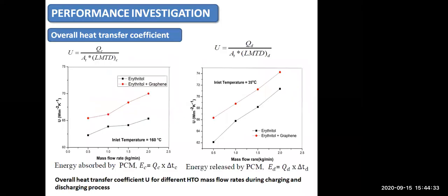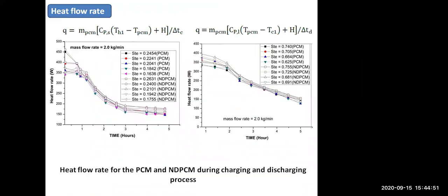Then performance investigation was done. The overall heat transfer coefficient increased 7% during the melting process and by 6% during the solidification process. This is a formula to find out the overall heat transfer coefficient. Then for the heat flow rate, at the beginning of the melting process, the heat flow from heat transfer fluid to the PCM increased by 3%, and for heat transfer fluid to the NDPCM is 4%, for 5% increase in inlet temperature. At the beginning of the solidification process, heat flow from PCM to the heat transfer fluid increased by 4%, and NDPCM by 7%.